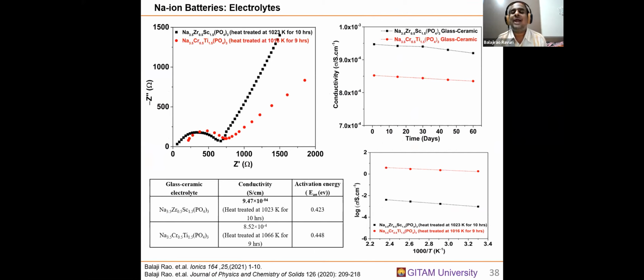That means we have kept those materials in ambient air for about 2 months. And these two materials have very good conductivity. There is no decrement in the conductivity, almost on the order of 10 power minus 4 Siemens per centimeter, which is a reasonably good conductivity, and is being used for our full cell battery purpose. We are at this stage.